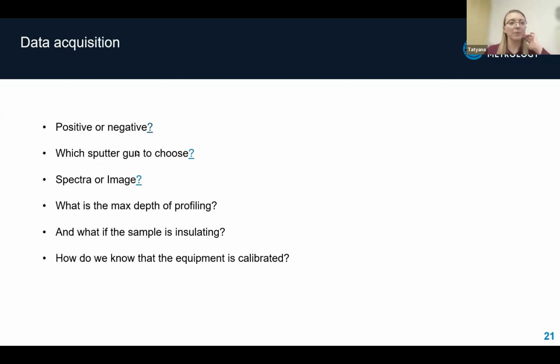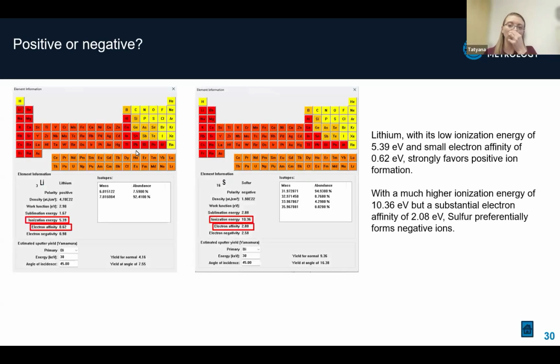Let's go to the data acquisition. So, what should we measure, positive or negative ions? In ToF-SIMS analysis, we can operate in either positive or negative ion mode. The efficiency of generating these secondary ions is quantified by ion yield, which is the fraction of sputtered atoms that become ionized. Looking at lithium and sulfur as an example, let's understand what determines the ion yield in positive or